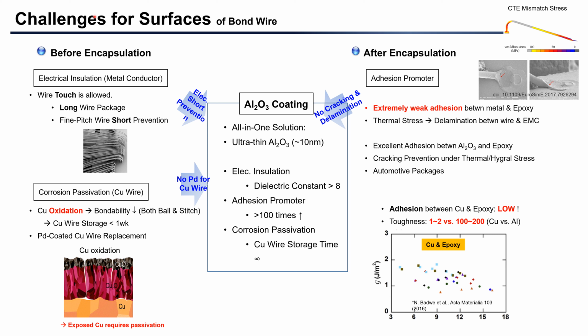Challenges for surfaces of bond wire. Challenges before encapsulation. Challenges after encapsulation. Before encapsulation, metal bond wire does not provide electrical insulation. Metal wires do not provide a corrosion passivation. After encapsulation, metal wire does not provide a good adhesion to epoxy molding compound. On the other hand, aluminum oxide coating can provide electrical insulation, corrosion passivation, and good adhesion to EMC.